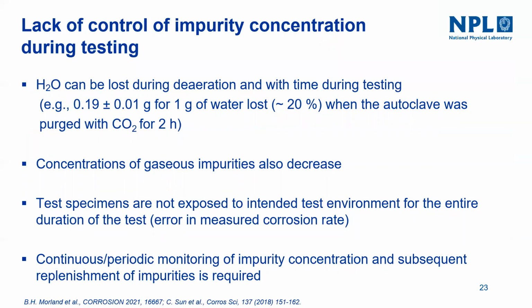The amount of water which is added into the autoclave is lost during the deaeration with time. And this will not be an issue if you have more water added in the autoclave. But if the water is close to the solubility limit, the loss of water prior to the testing or during the initial process can bring it lower than the solubility limit.